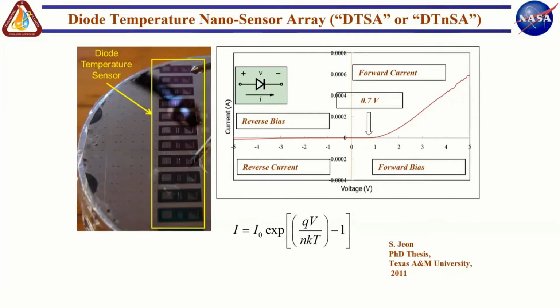And we found this particular configuration that was used for measuring skin temperature for cancer patients using diode nanosensors. So it turns out the forward direction current as well as the backward direction current in a diode scales with the temperature. So if you hold a diode to a particular voltage and you measure the current as a function of temperature, you can actually use that diode as a temperature sensor. So now we have a temperature sensor that's about 5 to 10 nanometers below the surface that does not create a surface bump and is able to measure temperatures. And we proved this for spray cooling applications.